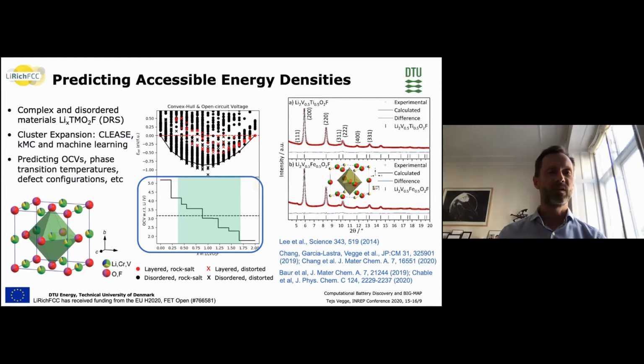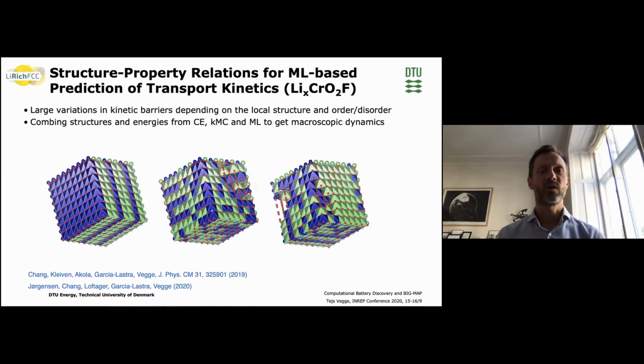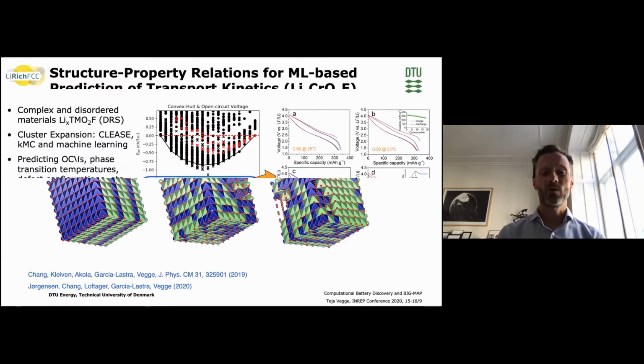And the next step in this type of modeling is really trying to establish structure property relationships that allows us to use these much faster accessible energies and structures from the cluster expansion technique, combine it with kinetic Monte Carlo and machine learning to be able to assess the power density or the diffusivity through a macroscopic system as a function of lithiation. And what you see here is the transition from a layered structure into a partly disordered structure.